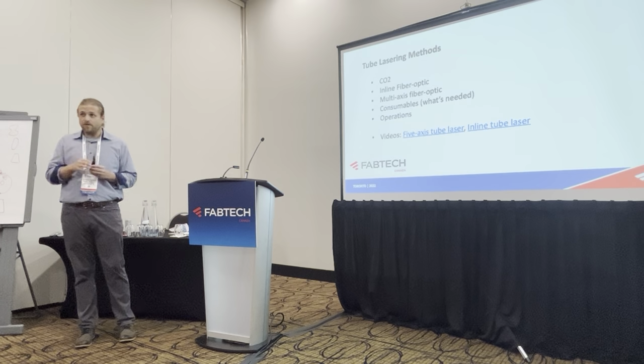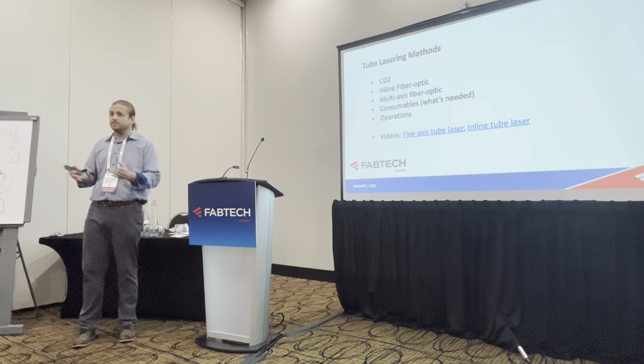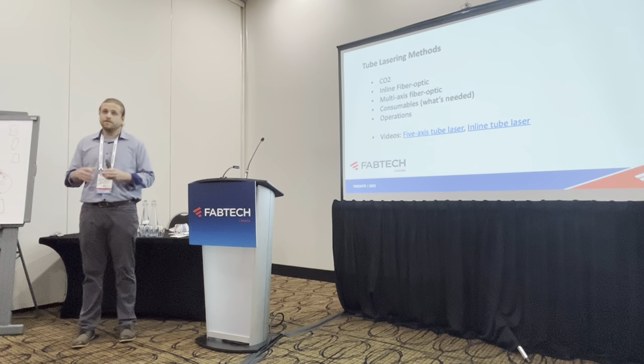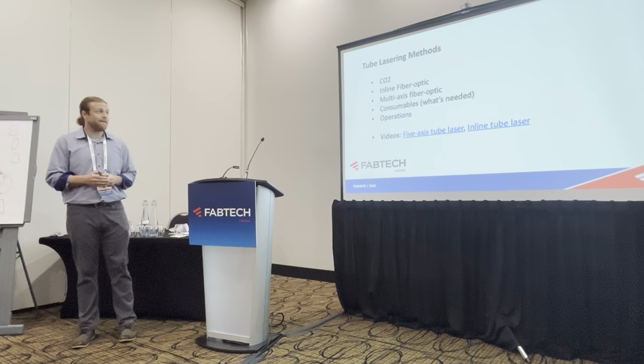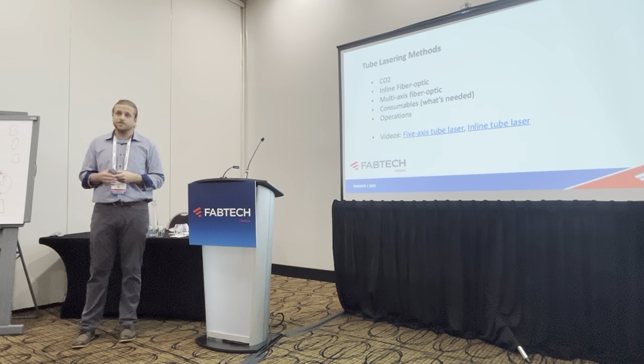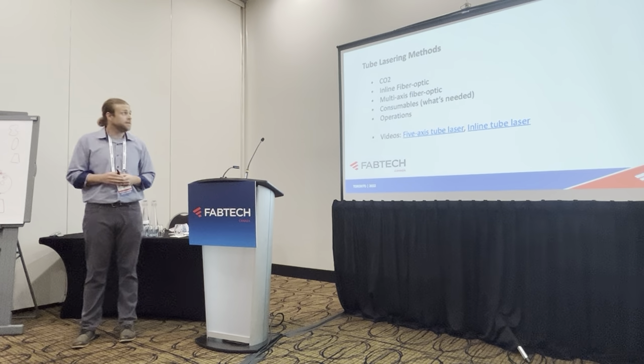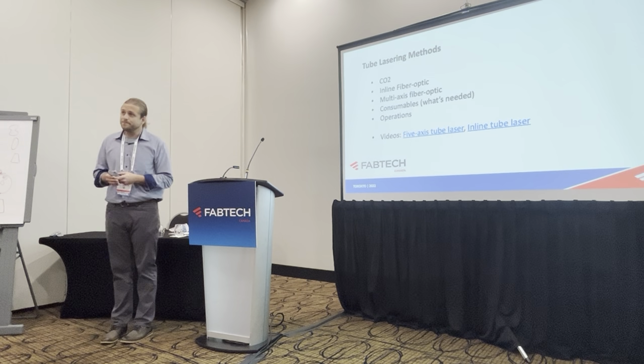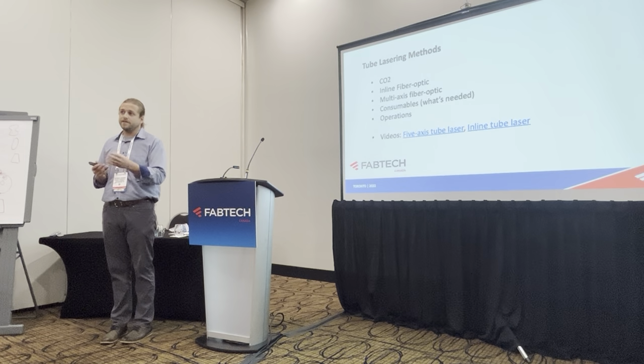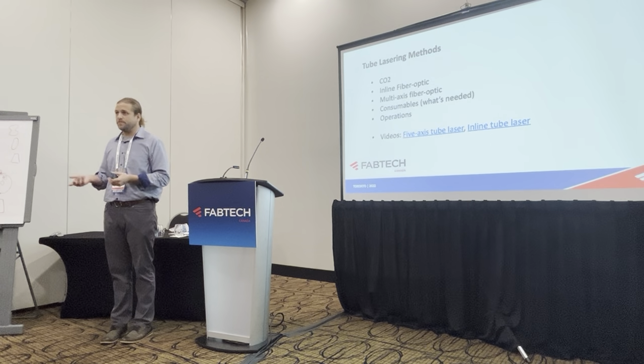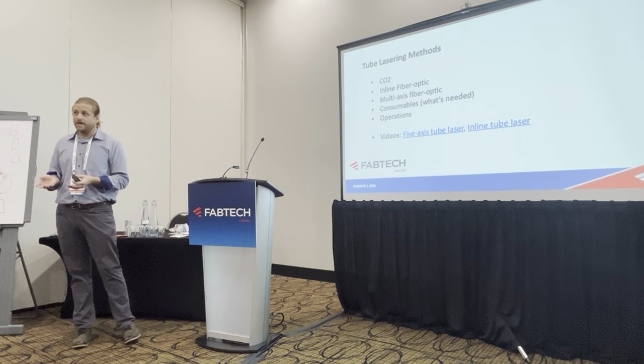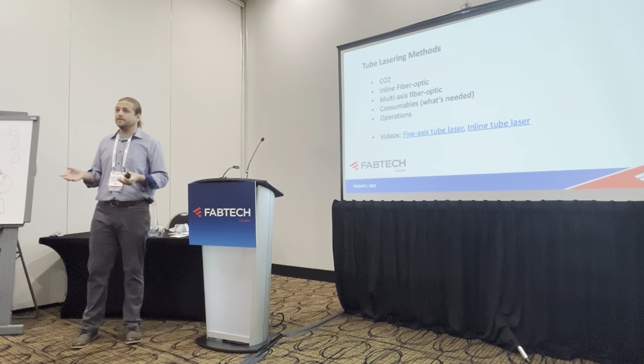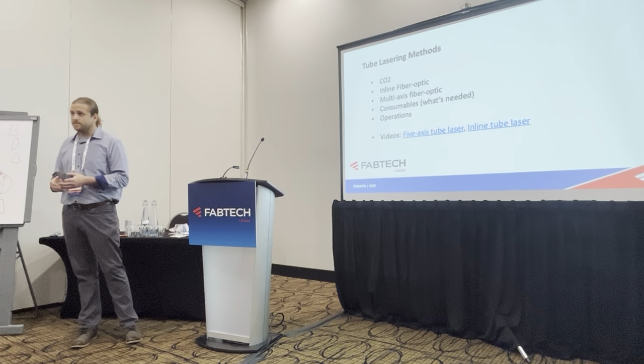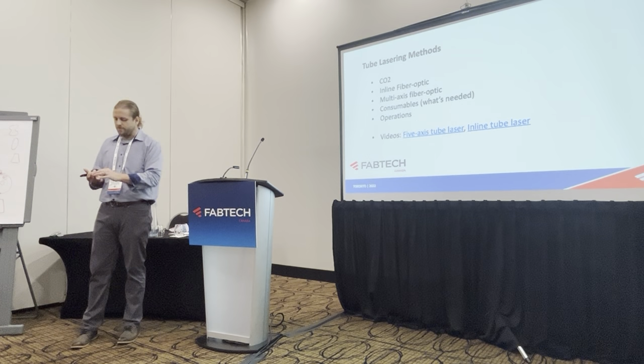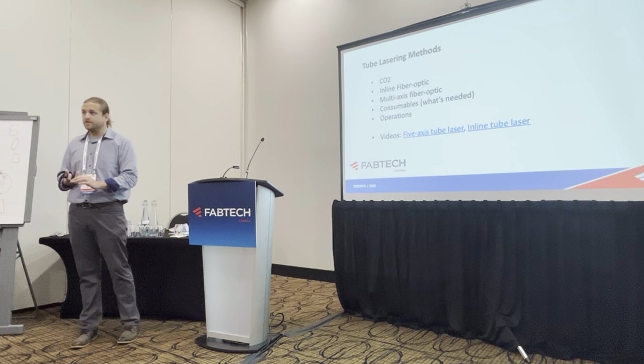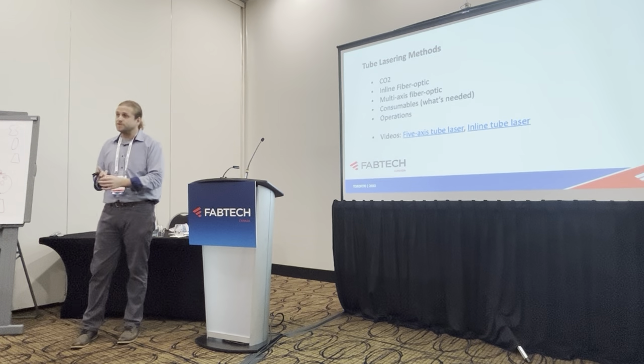CO2 lasers are a little bit older technology, but still in the industry. They work really well for thick wall, heavy structural tubing. You can cut with nitrogen or oxygen, but mostly with a CO2 laser, you're gonna cut with oxygen. Your other laser you have is a fiber optic tube laser. That's using a fiber optic to take that laser beam and cut the product. Mostly what you're using with a fiber optic tube laser is nitrogen, which is an inert gas, which helps eliminate your oxide layer. So when you cut steels with lasers, there's other assist gas too. You can have a mix, oxygen, nitro mix, things like that. But specifically oxygen and nitrogen is used most often.